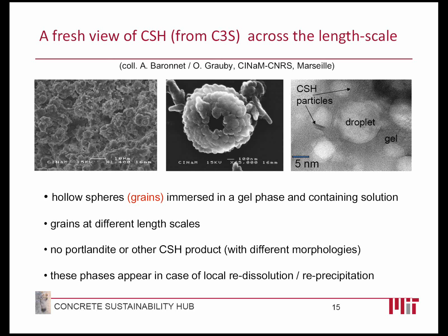And then if we move to the right to the scale of a few nanometers, so we go from microns to nanometer scale, we found out that one of those grains in the middle plot is also made of little grain CSH particles that have locally some layered texture. That's what we call CSH nanoparticles. So there are grains at different scales.